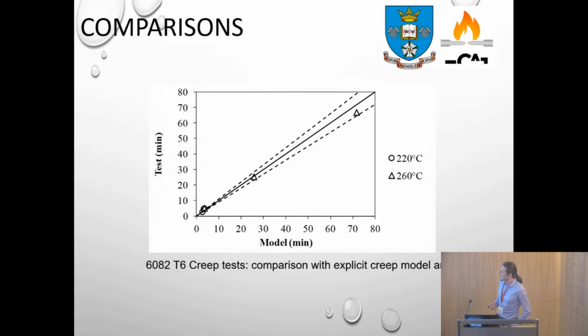When it comes to the analysis of aluminium columns, the explicit creep model analysis also showed good predictions with the same model that we use for steel. So it was the same background, the rotational spring column model. Only a different material model was used for aluminium. The Ramberg-Osgood model was used as a representative for the material model.